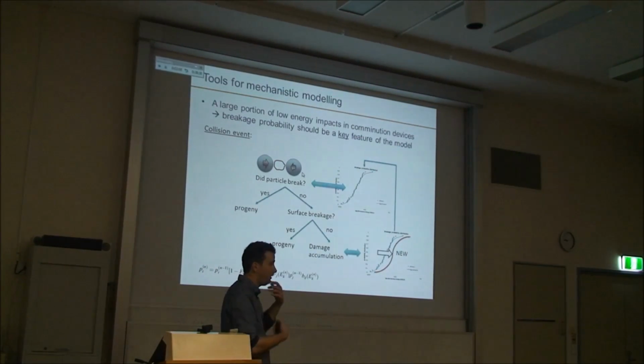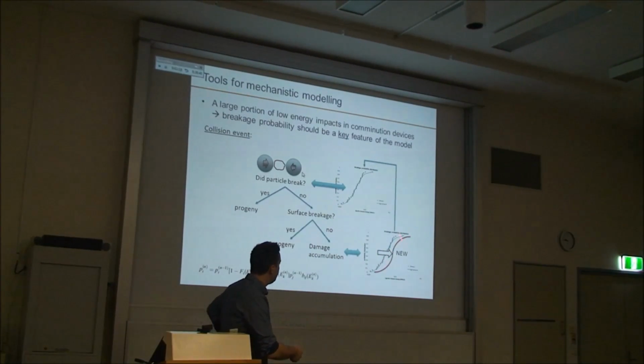As I said before, there is a model to model the damage accumulation, and what will happen is that the breakage probability is going to transform into a new one after the impact event. So this new breakage probability is then going to be fed back for the next step of simulation when the particle is being impacted again. Its properties actually will change.